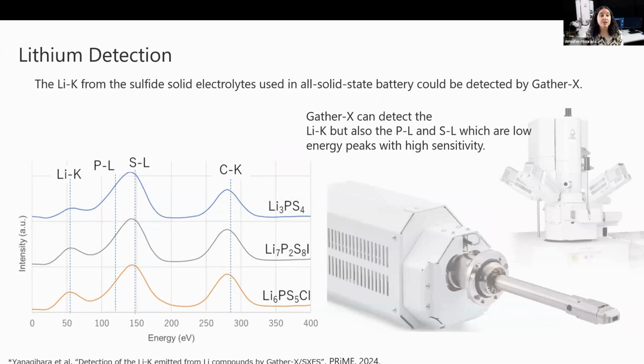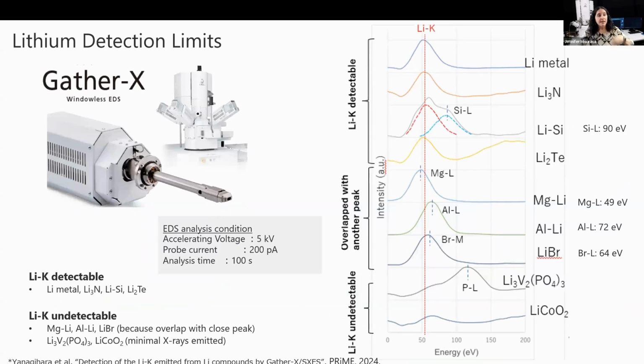And here's an example of a few sulfide solid electrolyte materials, which are also used in all solid state batteries. We can see that Gather-X can detect lithium in these compounds, as well as the phosphorus and sulfur characteristic L X-ray energies with high sensitivity. And here we can see the spectra for a selection of other lithium compounds related to battery materials. The top four, including lithium metal, are easily detectable with the Gather-X, and one of those is an alloy with silicon. You can see here that the peaks are overlapping, but can be distinguished with deconvolution.